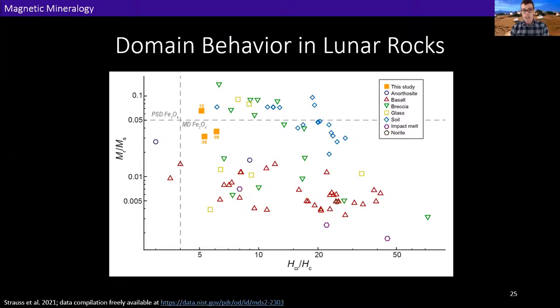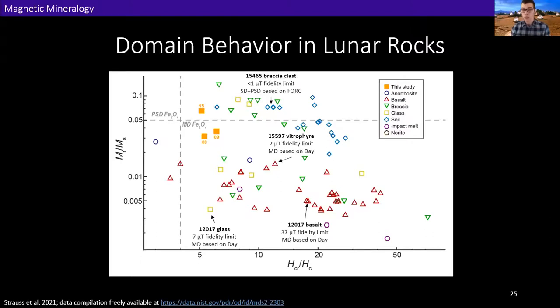And the data from our study is in the orange squares. I've also included these gray dashed lines to indicate domain state regions from the original day plot. So I'll note the positions of samples from a few recent studies on this figure, just by way of example. And you can kind of get a sense from this handful of points that the general trend we're hoping for does seem to hold. We see better lower fidelity limits as we look toward the upper left of the plot. However, there is a problem.